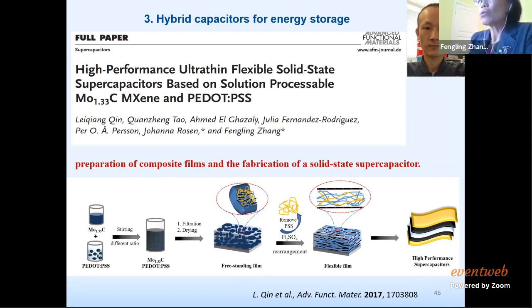In Linköping University, we have a group that works with MXenes. I think maybe you know it's a novel 2D material, and it has now become quite attractive. PEDOT:PSS is a high conducting polymer, but still not high enough. When we make this MXene and change the stoichiometry, we found that at optimized geometry, it helps to increase the capacitance of the capacitor. Here shows how we mix the film. We mix MXene with PEDOT:PSS, and then we filtrate to get the solid film.